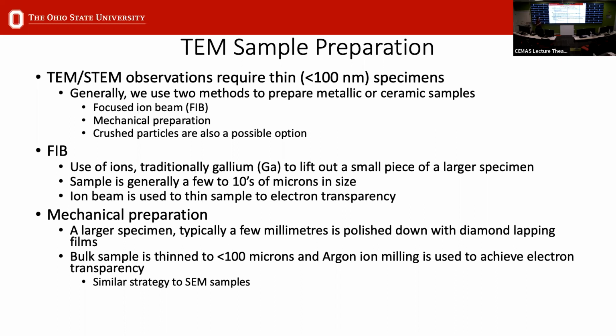So we generally use 2 methods: focused ion beam and mechanical preparation, but I'll also briefly discuss crushing your sample because that's the quickest way of doing it, and it might be overlooked in some cases. So in the FIB, you use ions, traditionally gallium, to lift out a small piece of a larger specimen. It's usually on the order of 10 microns, and then you use the beam to thin it to electron transparency.